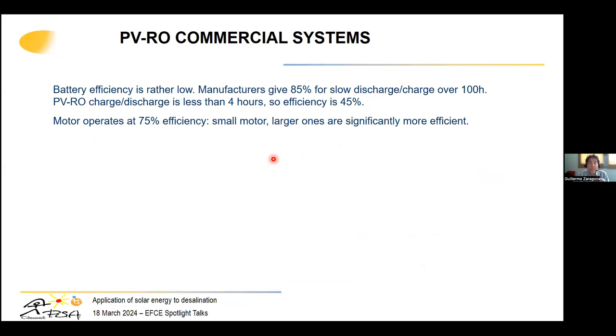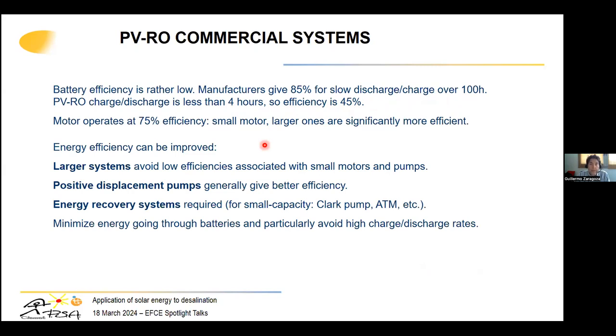But also the battery efficiency is rather low because of the charge-discharge cycles being very short. Manufacturers of batteries give 85% efficiency, but that's for very slow discharge-charge cycles over 100 hours. In the combination of PV and RO, we are using less than 4 hours, so the efficiency decreases to 45%. And also because of the size, motors operate at lower efficiency than in larger plants. So we have a problem with the efficiency of small PVRO systems. To improve the efficiency, we can use large systems to decrease the low efficiencies of the pumps and motors, use positive displacement pumps that usually give better efficiency, and of course, use energy recovery systems.